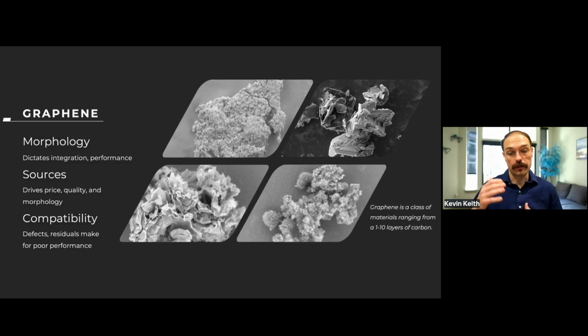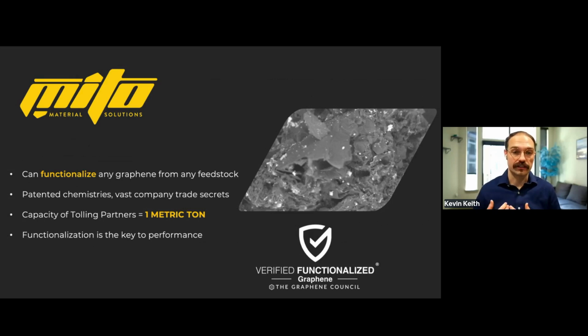And those two things really dive into the compatibility of the graphenes. So the compatibility is driven not only by the morphology and the sources, but by the defects, the residuals, and the crystallinity. And so in my world, there's no such thing as a bad material most of the time. It's that there are bad applications for the material. And so when we get these feedstocks in-house, MITO Materials functionalizes on top of that. So what we do is we create these chemistries using graphenes, graphene oxides, graphites, GRMs, if you will, and we can do this on any feedstock.